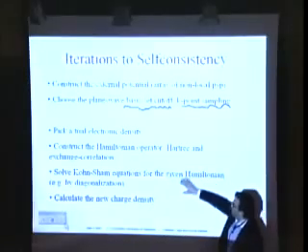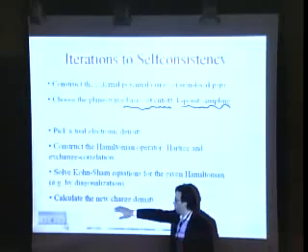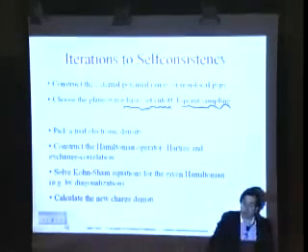So you need to find some schemes to evolve your charge density in a very smooth way. Maybe once you have calculated the new sum of eigenstates, you don't take that as the new charge density, but you just update your old charge density with 10% of what you have calculated now, to try to make the iteration to self-consistency very smooth.